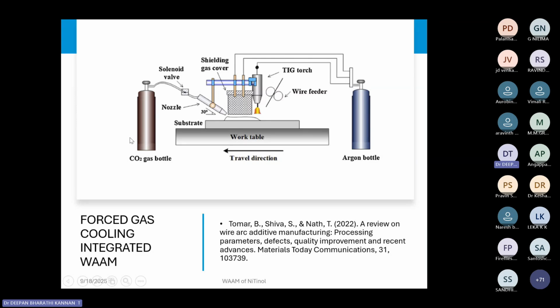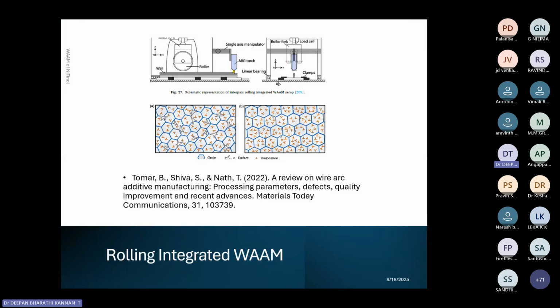So you can see that this is one option. What people could explore is that they can use a separate gas to cool the layer, monitor the temperature, and then we can build the next layer. This was explored in some other materials. This can be explored in nitinol, and we can combine wire arc additive manufacturing and rolling to get the benefit of rolling. So we know that the rolling process will help us to fine-tune the properties by altering the grain orientation. So this could be another option by combining rolling along with wire arc additive manufacturing.